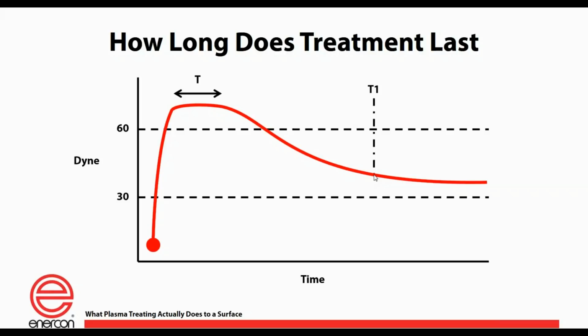And again, that's going to vary for every material. Let's say that I only needed to be above 30 dyne in this particular model to get good adhesion. Well, then basically my treatment now is permanent because I've started at a lower dyne and it's never going to get back to 30 in this example. So the treatment will last as long as the material stays active above the level with which you need to get that good bond.